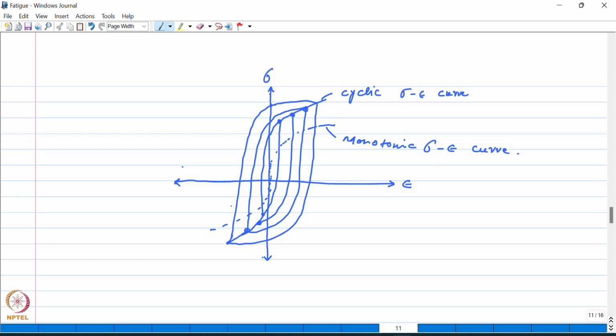And the cyclic stress strain curve can be defined by this equation, similar to the power equation which defines the plastic flow during monotonic loading. So n prime is known as the cyclic strain hardening exponent. Similarly, K prime is the cyclic strength coefficient.